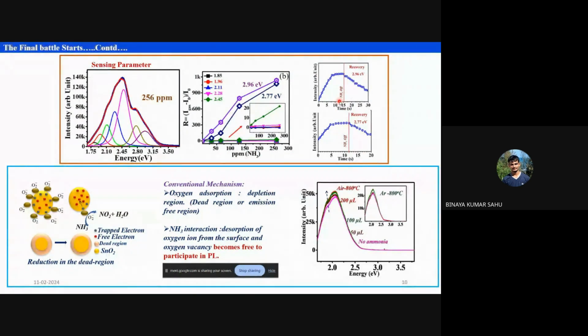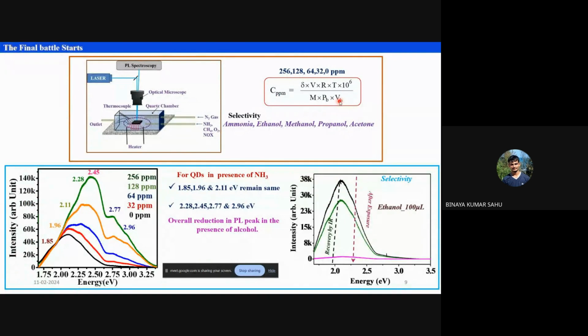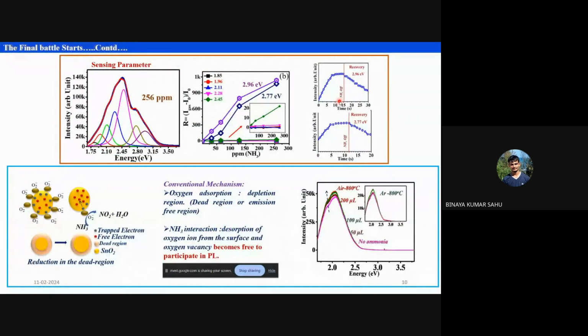And what is the third parameter when you are doing the sensing study? That is the recovery. Once the interaction with the ammonia is over, you remove the ammonia. How are you removing the ammonia? Basically, we are using some inert gas, nitrogen and all. So they remove your ammonia out from that chamber, and your sensor should go back to the normal condition. This is the intensity of a particular peak, this 2.96 and 2.77. Again, it's coming down to the original state. So it shows a better recovery.